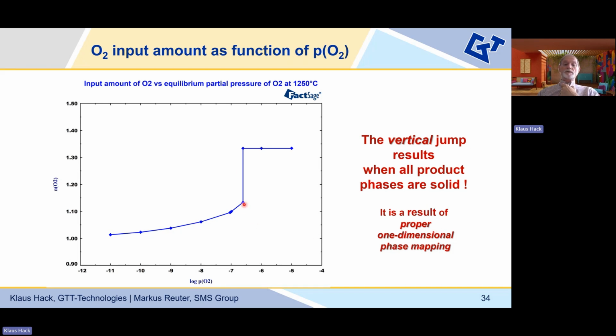And you can see there is a vertical jump here where the oxygen amount changes at one value of the oxygen partial pressure, because we are changing from the range where there is a continuous increase of oxygen amount while the molten oxide is picking up oxygen. We actually jump into the region where we have a fixed solid state, slag, and there we do not need to change the amounts any longer.